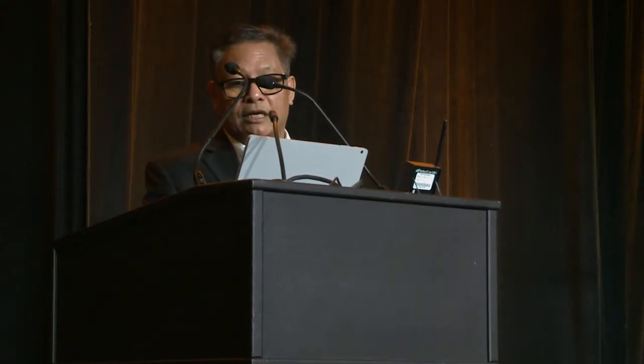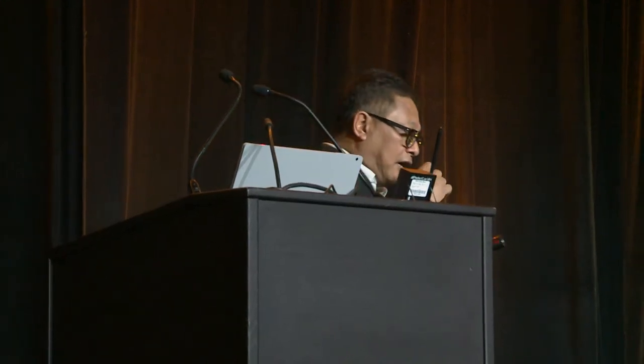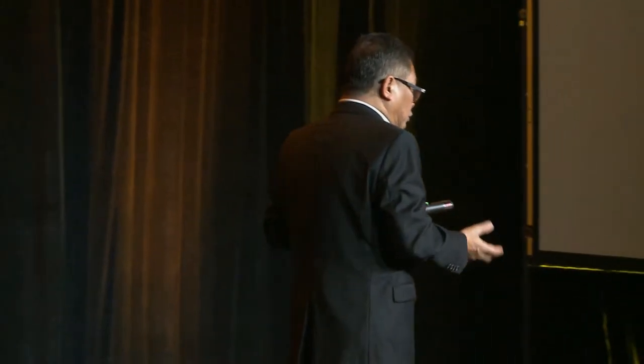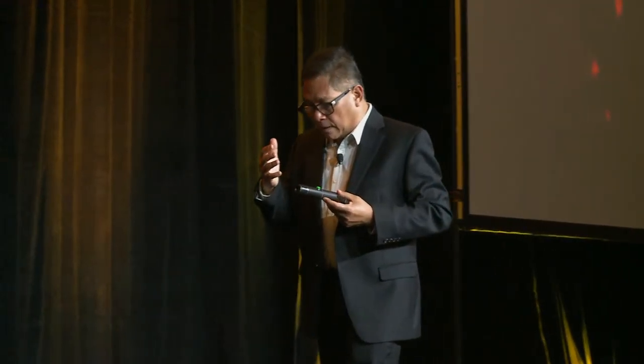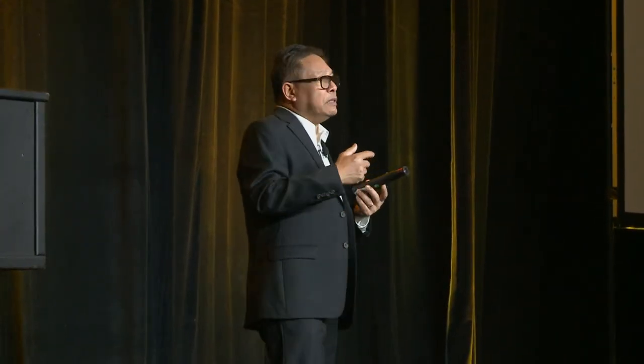And so, yes, we can apply the electric field, we can move the car, and this is just giving the example. So this kind of linear movement you can do, but there are a few things that we need to consider: the binding to the substrate has to be not so strong. And right now, most people are using electric field, so we need to have a dipole configuration put into your molecular device, so that if you apply the electric field, either positive or negative, depending on that, you can push-pull, you can drive.